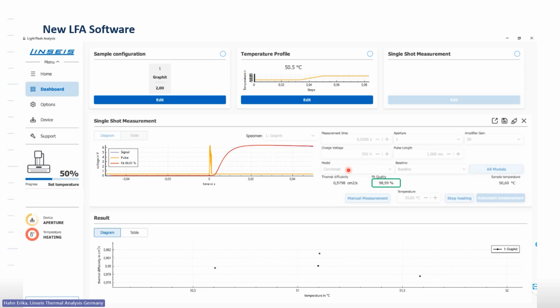During the measurement, the software will look like the following. Within the so-called single shot measurement window, one can perform manual tests, also do a manual heating up to a specific temperature, and, as mentioned, perform manual measurements. However, mostly one uses the software in the automatic mode, with the automatic measurement, where the set temperature profile is run automatically. And here you can see how it will look during a test. You can see the individual shots taken at a target temperature of 50 degrees Celsius, as we just have two temperature steps set up here.